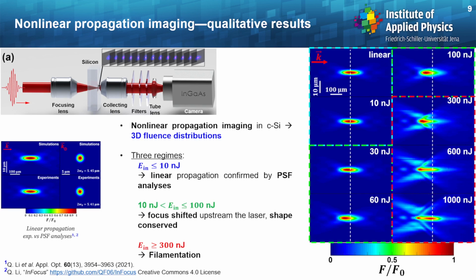And then what you can see here, when we increase further the input pulse energy, like more than 300 nanojoule, we are clearly in the filamentation regime, especially for the highest pulse energy of 1 microjoule, where you can see those multi-foci, which are related to the focusing and defocusing dynamics.